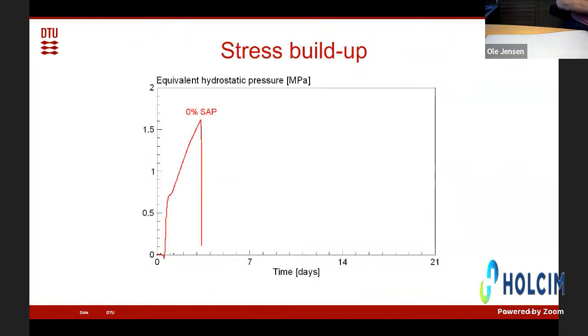I will show you one set of graphs in this talk. It shows how stresses develop in ultra-high performance concrete during restrained hardening. So this is a 200 megapascal concrete without any superabsorbent polymers. During restrained hardening, stresses build up, and after 3 days, the concrete cracks as indicated by this relief of stresses.